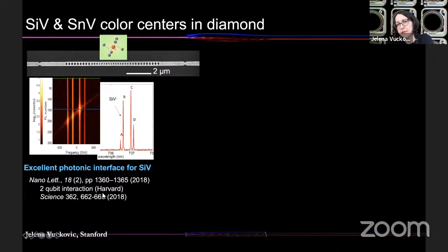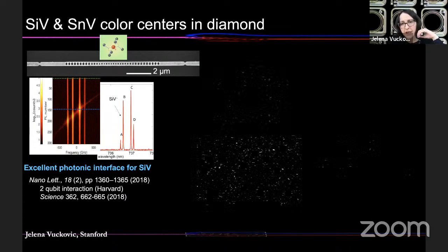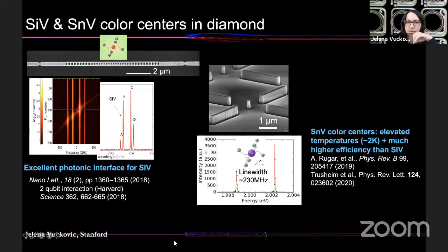And also recently at Harvard, they have demonstrated interaction and entanglement between two silicon vacancies inside of the same diamond cavity. And they use a magnetic field to tune them onto resonance with the cavity. So they've shown superradiance and interaction of two qubits. Of course, that particular platform is not exactly scalable because they use a magnetic field around the resonator, and it worked in that particular case, but it could not really work in an arbitrary case. But I'll show you some of the other ideas that we and others are pursuing to scale this to a larger number of emitters.